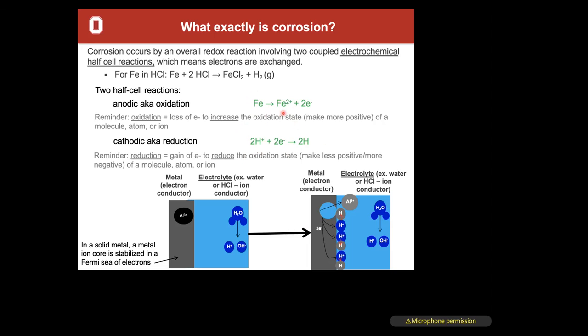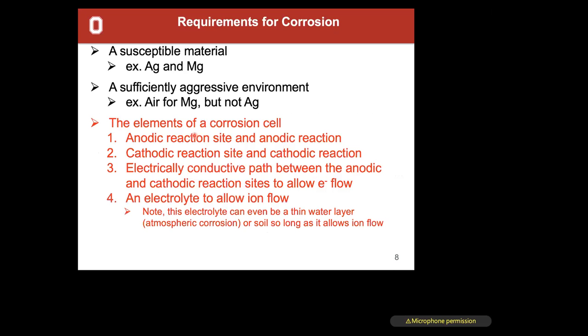So we get one reaction losing electrons, and that reaction for corrosion specifically means it's coming from the metal state and making an ion. Those electrons can't just hang out with nowhere to go. They go to this cathodic reaction, which is consuming those electrons. So here in the example, H+ in the water is taking up the 2 electrons to make adsorbed hydrogen. And typically that hydrogen will combine with another adsorbed hydrogen and bubble off and go away. So that's the skinny of what's happening, the one slide guide to what actually is happening with corrosion in these electrochemical reactions.